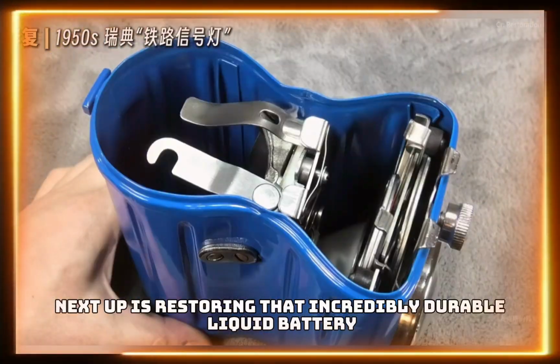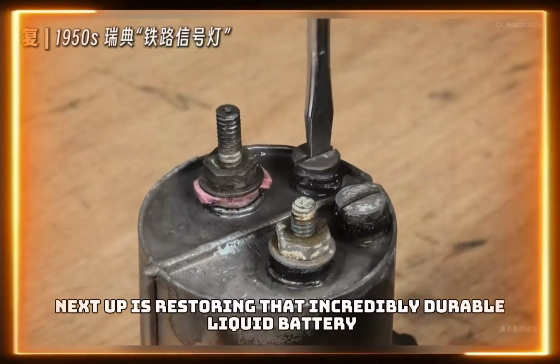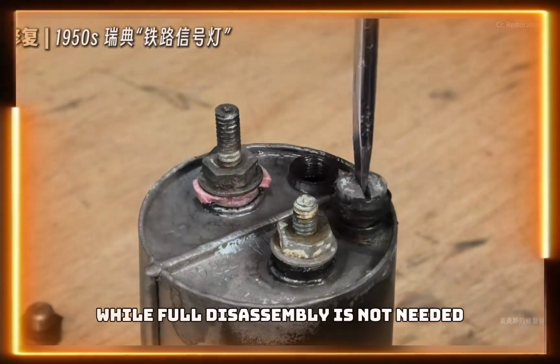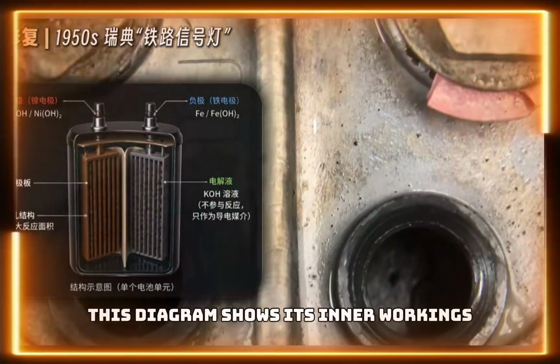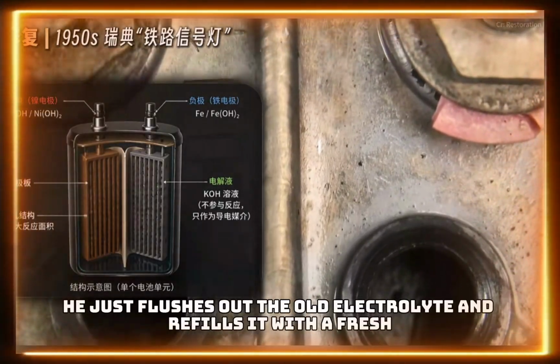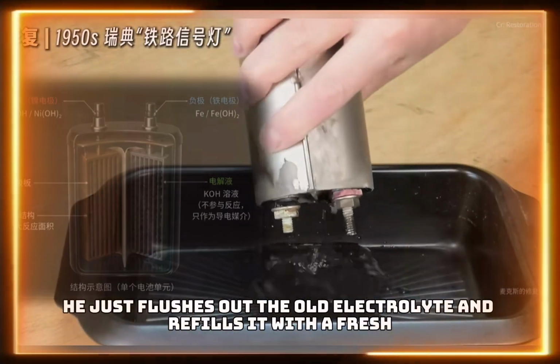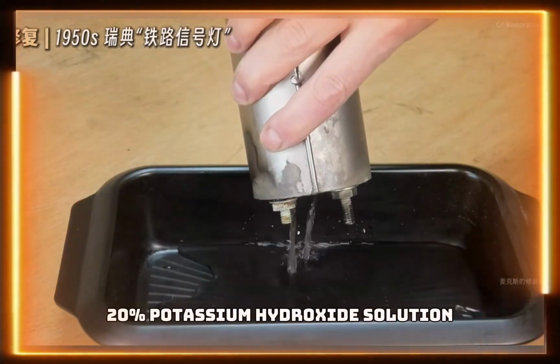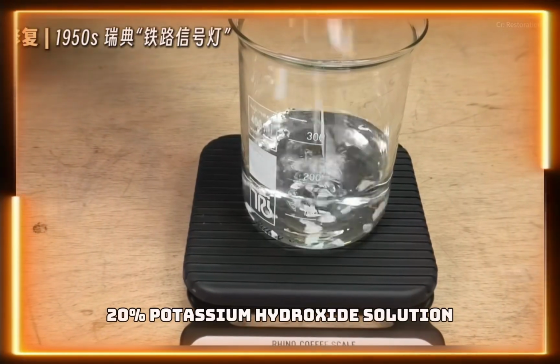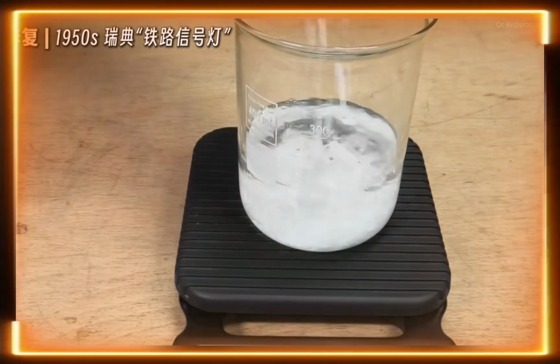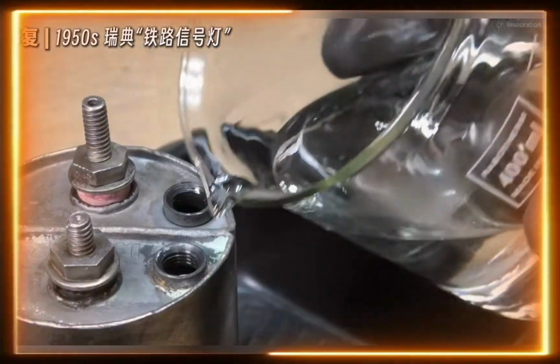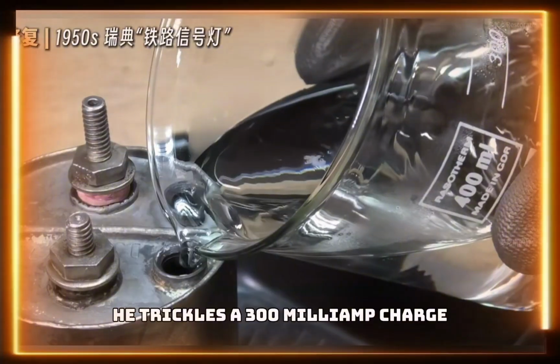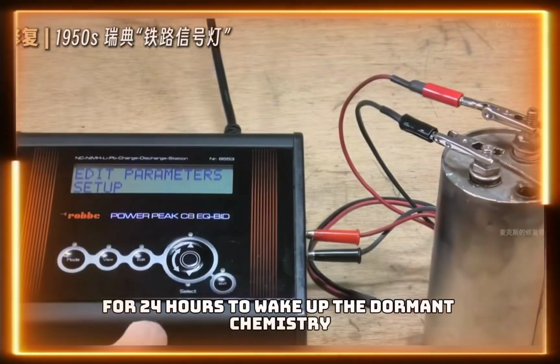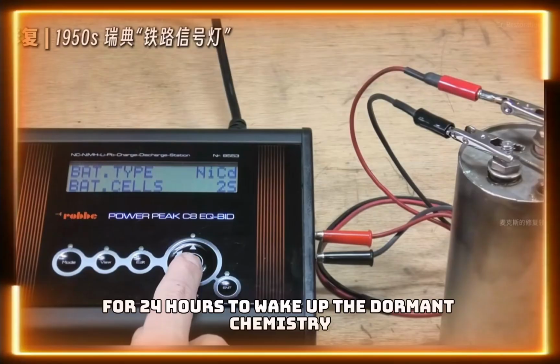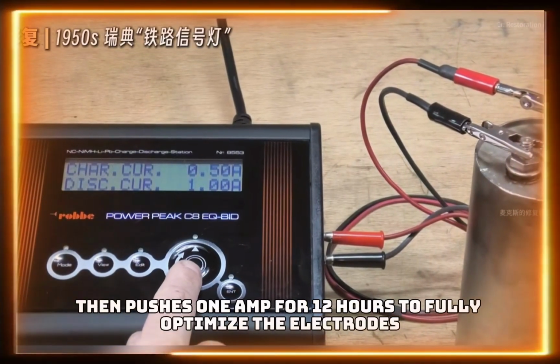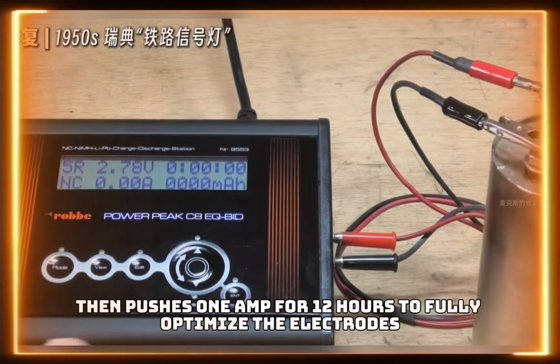Next up is restoring that incredibly durable liquid battery. While full disassembly is not needed, this diagram shows its inner workings. He just flushes out the old electrolyte and refills it with a fresh 20% potassium hydroxide solution. He trickles a 300 milliamp charge for 24 hours to wake up the dormant chemistry, then pushes 1 amp for 12 hours to fully optimize the electrodes.